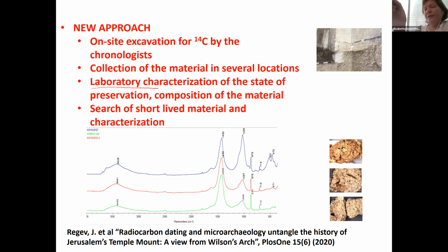And also, if we were collecting mortar from different locations here, and we think this is the same event, we characterize this mortar with the infrared. And as you can see from the spectra, these are three different mortars from three different periods in the Wilson's Arch structure.